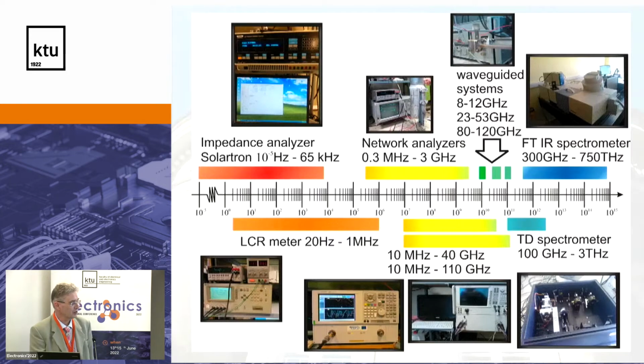Of course, there is the LCR meter, which is the usual simple capacitance method, where you measure the capacitance, and from that you calculate the electric permittivity, real and imaginary parts. And then you use different vector network analyzers, which go up to 110 gigahertz. And in this range, we use a coaxial line. And later I will tell why we use a coaxial line only up to 2 gigahertz, up to here. Because due to high dielectric permittivity, you will face huge problems, which I will explain a bit later.